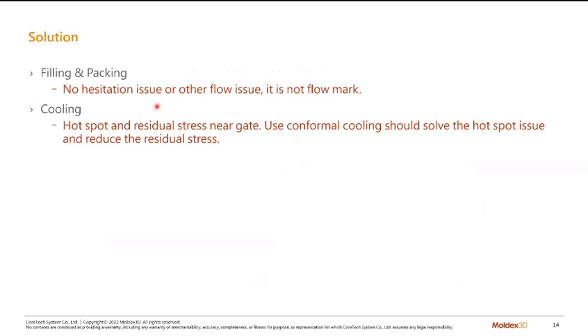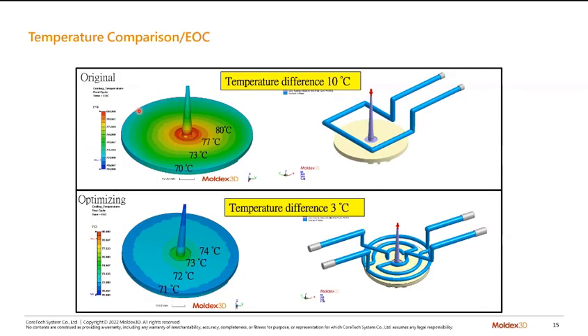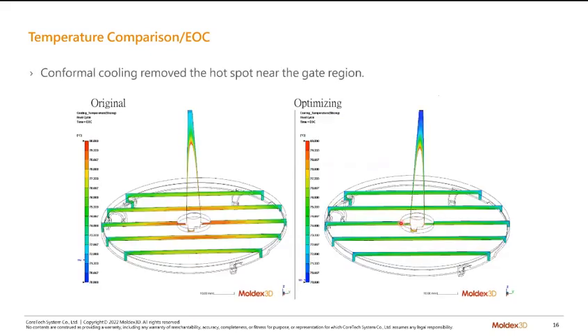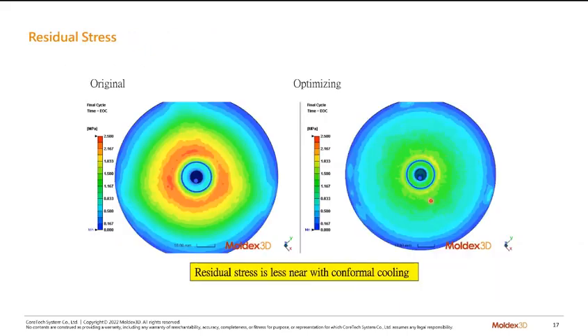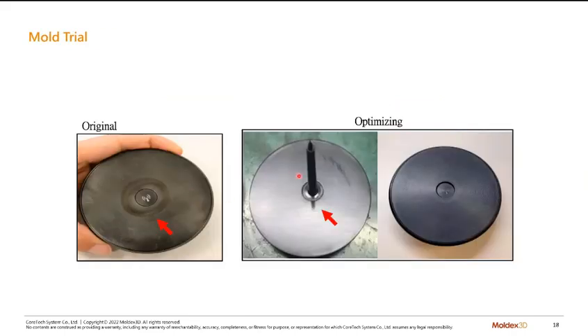Okay, so they come up with a solution. First, they find out it's not a flow mark caused by hesitation; this issue is caused by residual stress and related to the temperature distribution. So using conformal cooling should fix this. They come up with this new conformal cooling design to make the temperature more uniform inside the cavity, and you can see that it's roughly a 3 degree difference. If we look inside the cavities, the temperature is quite uniform compared to the original one. Then they check the residual stress, and you can see that it is much lower than the original. So they use this design for the tooling, and the residual stress was removed.